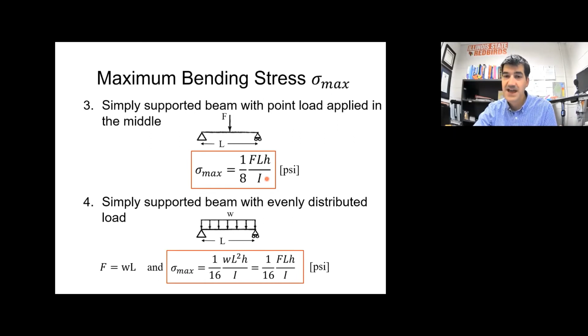So using that, you can predict the F at which you're going to reach the stress that it fails. Once you look up the flexural strength of your material, you can solve for the F that is going to cause the material to fail. So that is the way that you can make your prediction in lab 8 for when your beam is going to fail.